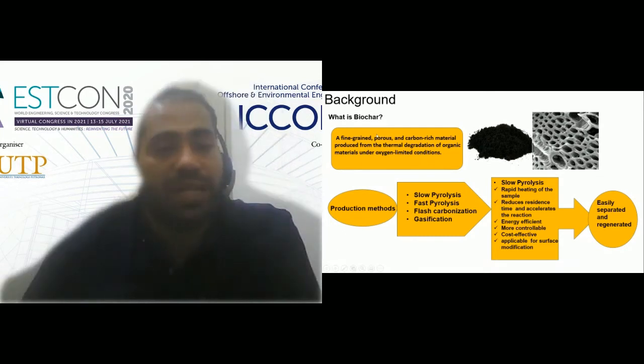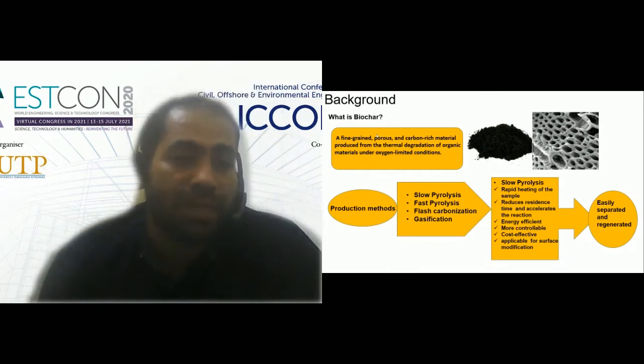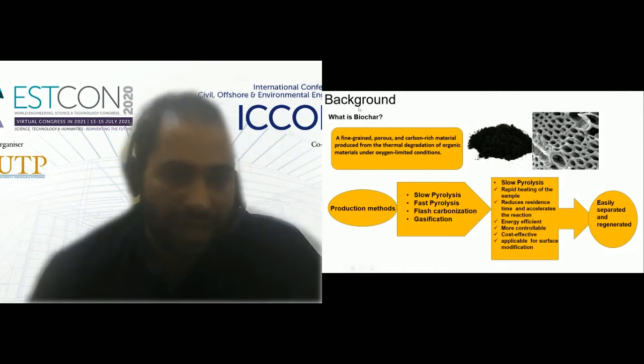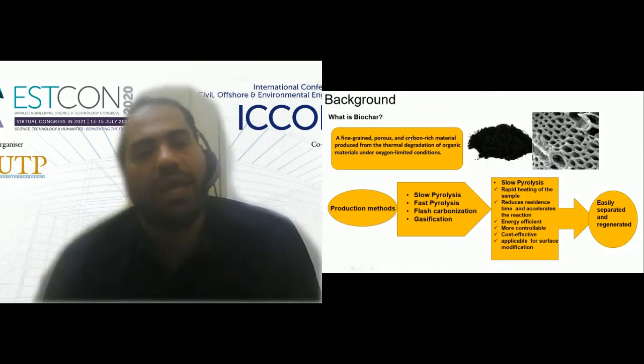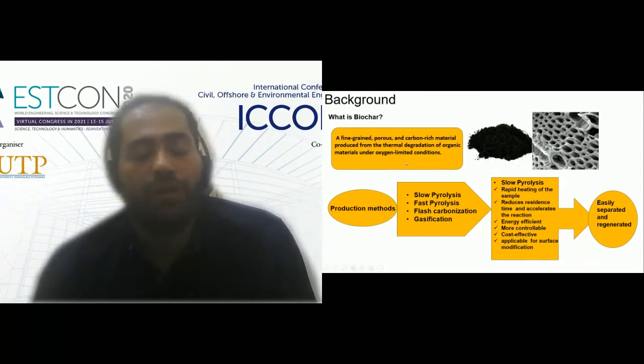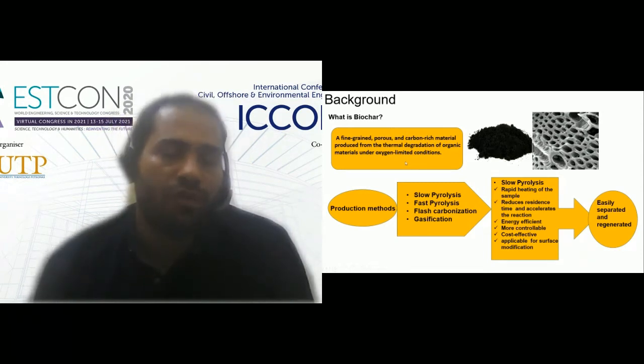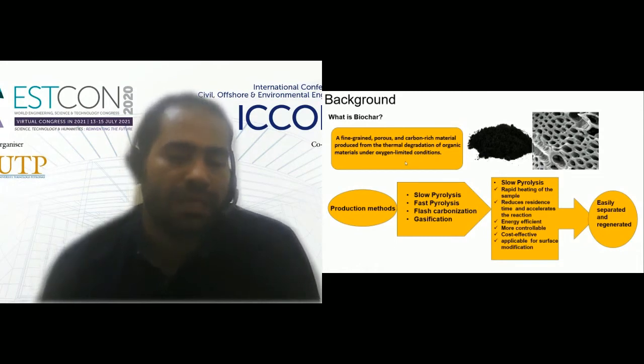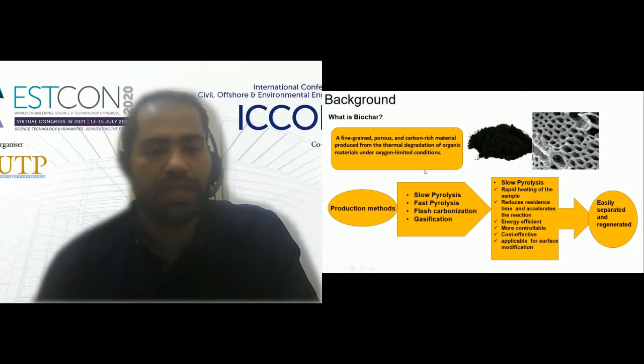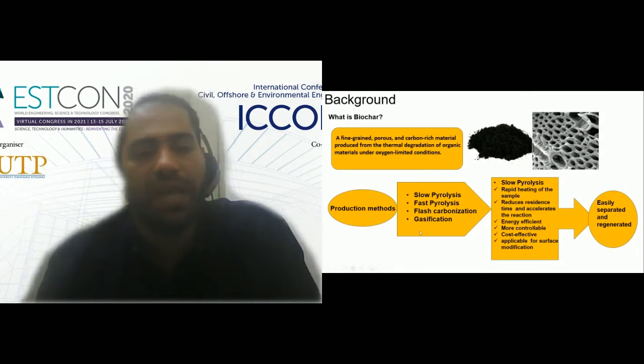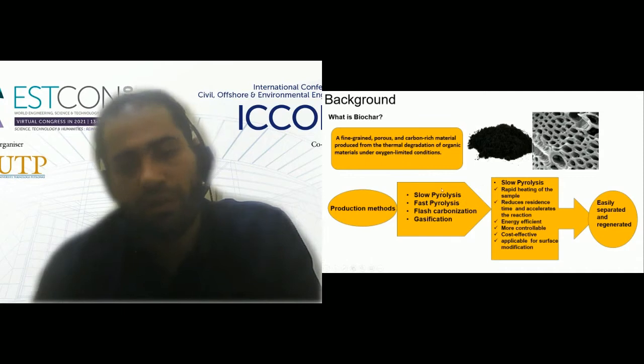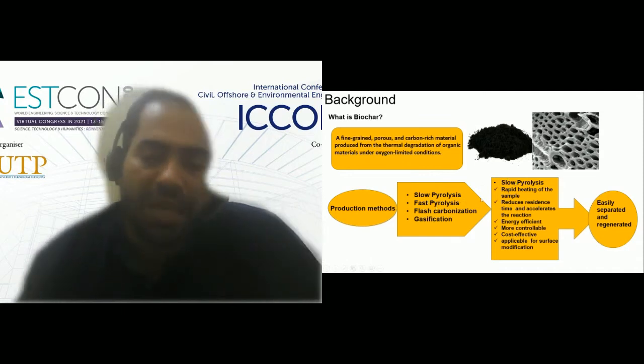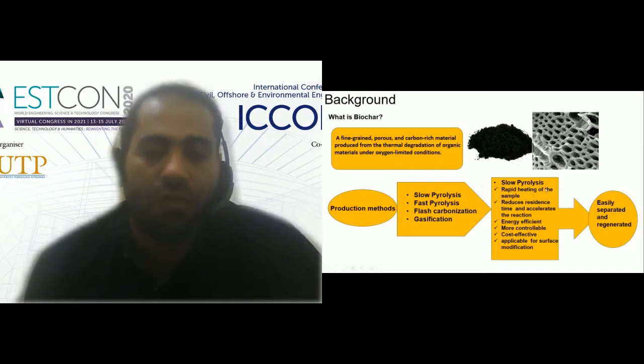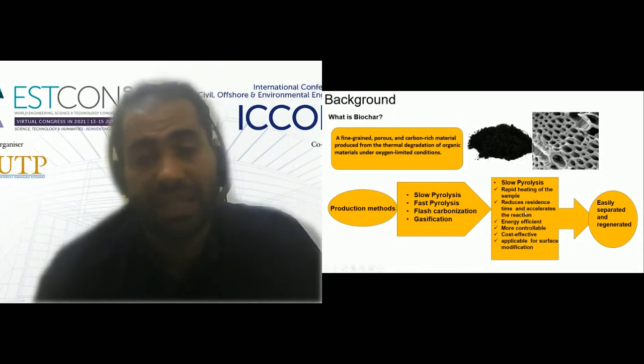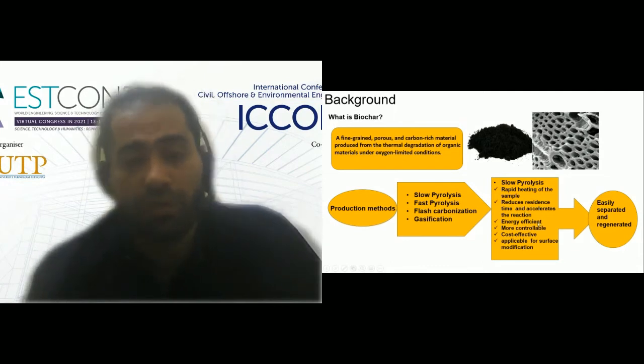What is biochar? It's a fine-grained, porous and carbon-rich material produced from thermal degradation of organic materials under oxygen-limited conditions. To produce biochar, there are many technologies and production methods like slow pyrolysis, fast pyrolysis, flash carbonization, and also gasification. We use slow pyrolysis. Why? It has a lot of advantages: rapid heating of the sample, reduced residence time, accelerated reaction, energy efficiency, and it is also more controllable.